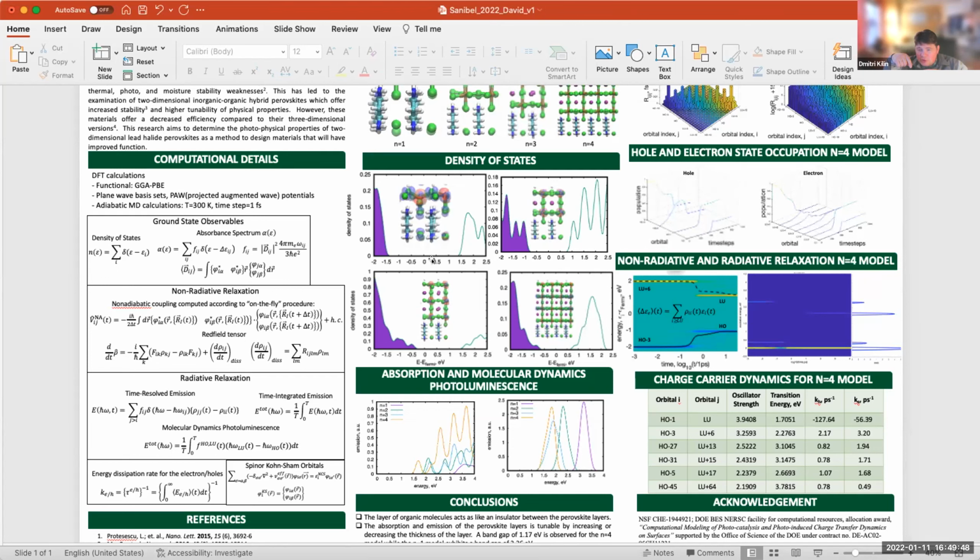So there is a distribution of possible transition energies, like an ensemble. Different methods address or ignore some of these effects in calculations. If you have a rigid crystal, then these effects are less pronounced. If you have a small molecule or soft molecule made of organics, then all three effects will be much more pronounced.